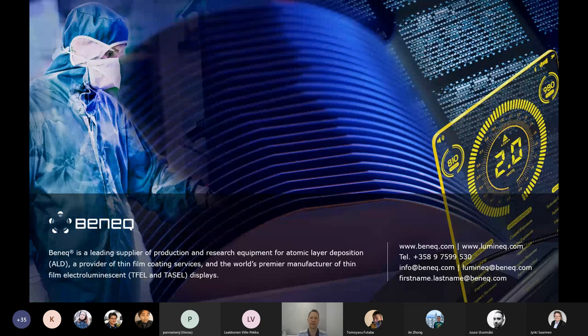But that's what happens. And different ALD coatings also do that in a slightly different way. The best for this kind of thing is to use some amorphous coating. Some ALD coating materials can also be crystalline, and then the crystal growth can actually cause more roughness. So an amorphous material would be recommended for smoothening the surfaces.